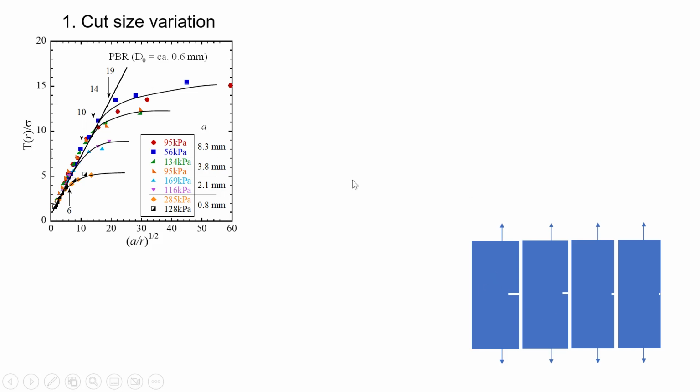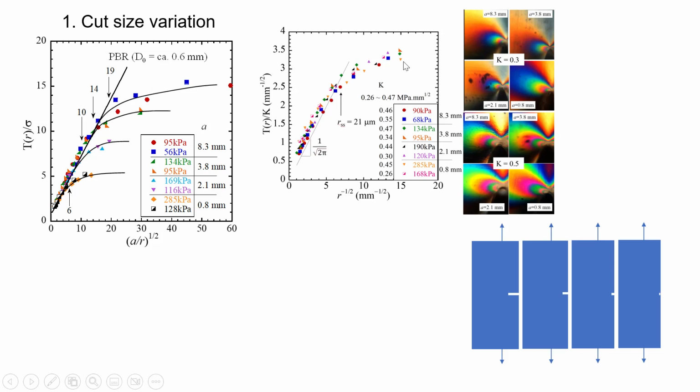So this was standard fracture mechanics. We're just going to show that Gc or Kc is material specific, independent of cut size and geometry. For example, this is just a different way of plotting it, because instead of putting 1 over r, I had the cut size there, so that's why the plateau shows at different places. So you spread them out, a very nice way of doing it. And you can also collapse them by plotting this way and normalizing your stress with K, and you get a sort of master curve indicating a common place of plateauing of your stress.